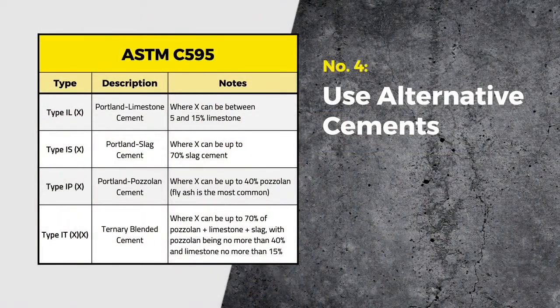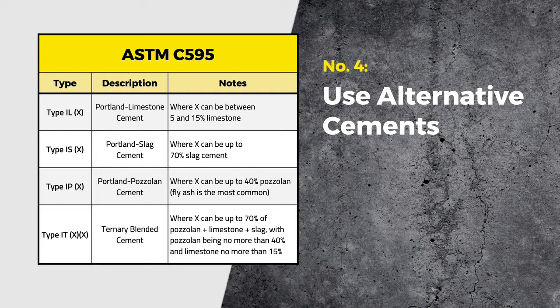There are several alternatives to Portland cement, but the most common are called blended cements, which combine ordinary Portland cement with other materials. The most common type of blended cement is Portland limestone cement, often called PLC for short, or technically ASTM C595 Type IL cement. This blended cement combines up to 15% limestone interground with Portland cement to make a cement with a carbon footprint up to 10% lower than ordinary Portland cement, with performance identical to — and in some cases better than — ordinary Portland cement.